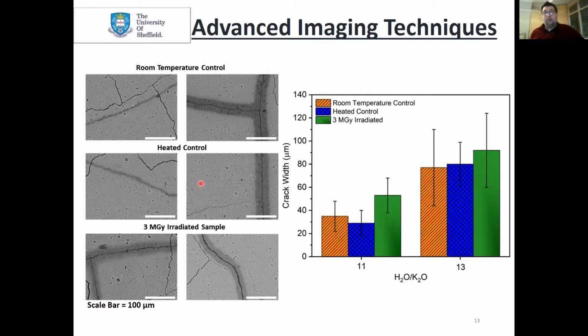The reason for impregnating the epoxy is that if you impregnate it pre-sample analysis, you don't get cracks like this forming from the vacuum of the SEM, which would cloud your results and make you see things that aren't quite there.